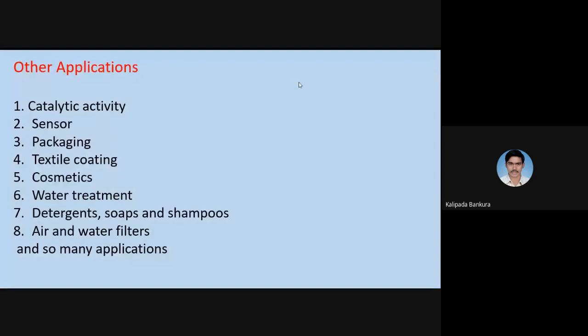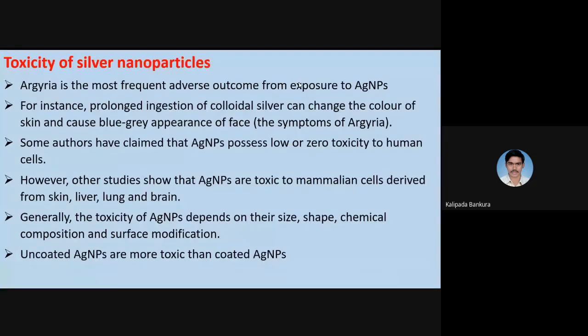Toxicity of silver nanoparticles. Argyria is the most frequent adverse outcome from exposure to silver nanoparticles. For instance, prolonged ingestion of colloidal silver can change the color of skin and cause a blue-gray appearance of the face. Some authors have claimed that Ag nanoparticles possess low or zero toxicity to human cells, but other studies show that silver nanoparticles are toxic to mammalian cells derived from skin, liver, lungs, and brain. Generally, the toxicity of silver nanoparticles depends on their size, shape, chemical composition, and surface modification. However, uncoated silver nanoparticles are more toxic than coated silver nanoparticles.